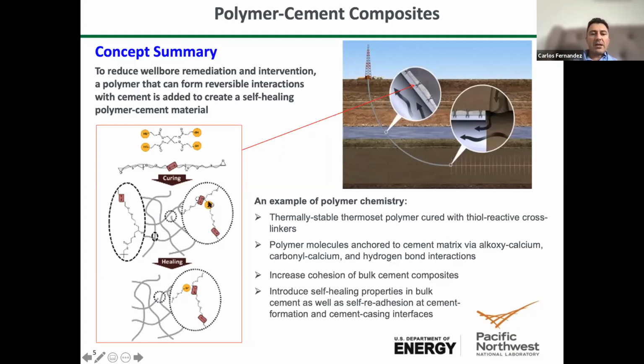We thought that if we have polymers with different functionalities in the backbone, and that's why I asked the question about the fibers, functionalities that can interact not only with the polymer itself, like the sulfur-sulfur exchange, but also with the cement components, like the calcium or the oxygen of the aluminum silicates, or the calcium silicate hydrates of cement, via hydrogen bonding, coordination bonds, or electrostatic interactions. In this case, you see here an epoxide with an oxygen. It's hard to see, but when that oxygen has a negative charge, forming an alkoxide, it can interact with the calcium, for example, and form a calcium-oxygen bond.